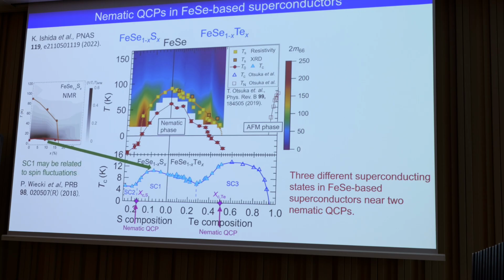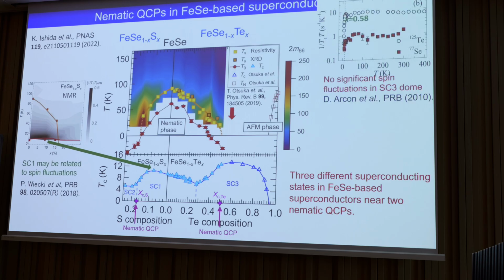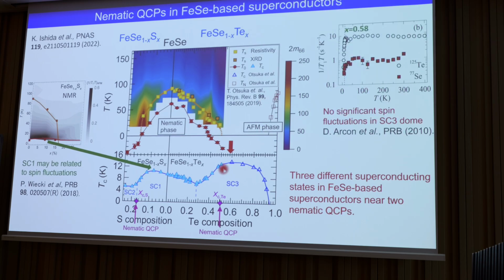However, if you go to the SC3 side, and look at the NMR data, 1 over T1T is pretty constant as a function of temperature. This indicates that there are no significant spin fluctuations in this SC3 dome, at least at low energies, if you believe these NMR measurements. So it is likely that SC3 is related to the pure nematic QCP. So I suggest that this SC3 is coming from the nematic fluctuations rather than spin fluctuations.